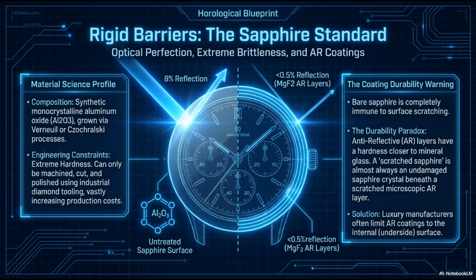Look at the central diagram showing the reflections. Untreated sapphire is highly reflective, bouncing about 8% of light back at the wearer, making the dial unreadable in bright sun. Therefore, we apply anti-reflective, or AR, coatings. Microscopic layers of magnesium fluoride, MgF2, are vapor deposited onto the surface, dropping reflection to under 0.5%. But heed the coating durability warning on the right.